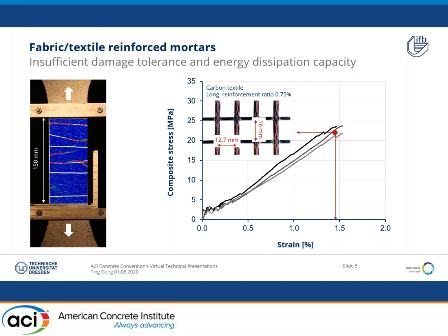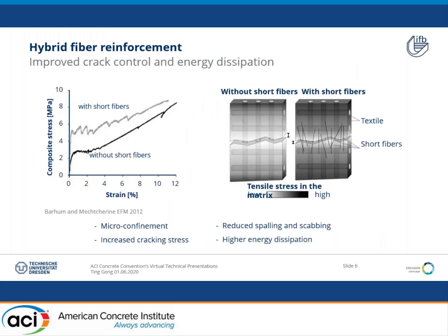First of all, I would like to start with two types of commonly used fiber-reinforced material. The first one is continuous textile-reinforced concrete. TRC possesses quite good strain capacity and quite high tensile strength. However, the disadvantages can be limited multiple cracking propagation, early crack localization, and a relatively large crack width. To improve the TRC behavior, researchers have worked on hybrid fiber reinforced concrete, for example, adding short glass or carbon fibers to the composite.